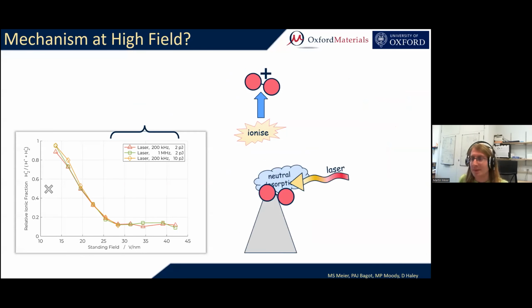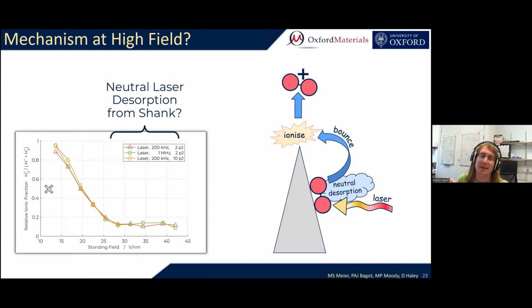We thought about the following. The fact that we are observing hydrogen in laser mode, which we do not observe in voltage mode, almost begs for an interpretation that there's somehow something happening outside the field of view on the tip shank. So maybe the laser has some interaction with the sample body that is triggering all of this extra hydrogen. Could it possibly be something like this? The laser is triggering a neutral desorption on the tip shaft outside the field of view. The released hydrogen is turning into imaging gas very quickly for a very brief amount of time. And this may really be just in the region of nanometers, this flight path here, until it eventually ionizes ahead of the tip and flies into the detector. It's something that we can't prove and we can't disprove, but so far it seems like the best fit to what we are seeing. At least we have not had any better ideas. Make sure to email me if you got one.